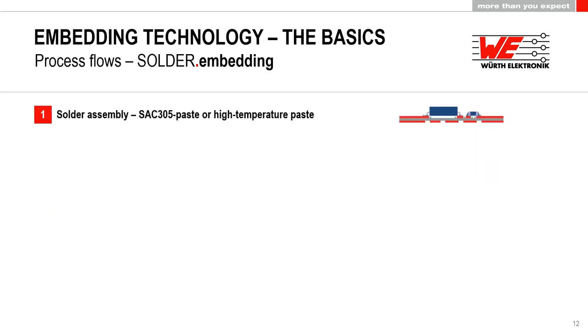The third process flow I want to show you is the solder process flow. And this is probably the one which you are most familiar with because the soldering which we are doing here is really comparable, and I would say the same, as you would use it on an outer layer. So we normally use a standard lead-free solder paste to assemble the components onto a pre-structured inner layer core. And this inner layer core is only slightly modified compared to a standard inner layer core.